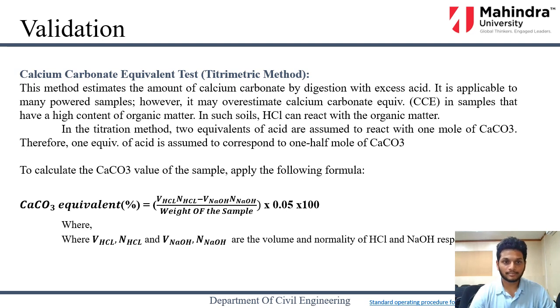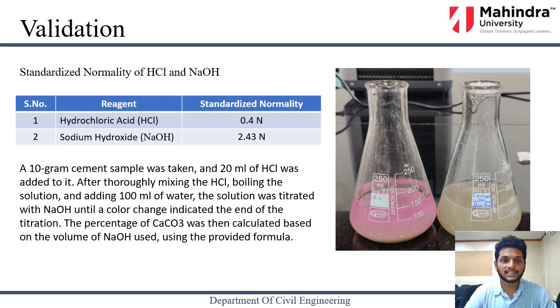Firstly, we standardized the normality of the HCl and the NaOH, or sodium hydroxide. The standardized normality of hydrochloric acid is 0.4 normal, and the sodium hydroxide is 2.43 normal. For this test, we took a sample of 10 grams of cement and added 20 ml of HCl. After thoroughly mixing the HCl and boiling the solution, we added around 100 ml of water to the solution, and then it was titrated with sodium hydroxide until the color change was indicated, which we can see in the picture.